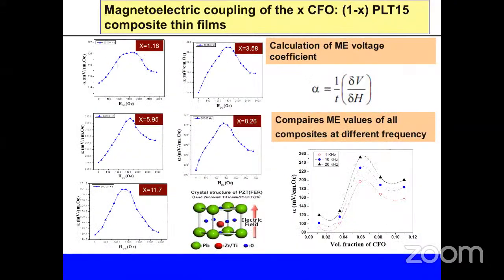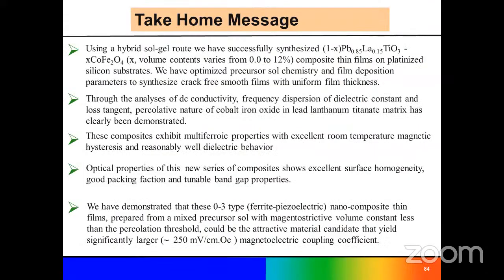So finally, for this material, we took the magnetoelectric coefficient, which is very important for memory device applications. If the magnetoelectric coefficient is very high, that means we can tune this material by applying voltage or current. It is correlated with the magnetic and electrical property. That means if you apply an electrical field, it gives a high magnetic value, or if you apply a magnetic field, it gives a high electrical value. That means the power consumption of the memory device is very low. So here we conclude that we got around 250 millivolt per centimeter per oersted magnetoelectric coefficient, which is very high, and it can be usable for this memory device, which consumes much less power.